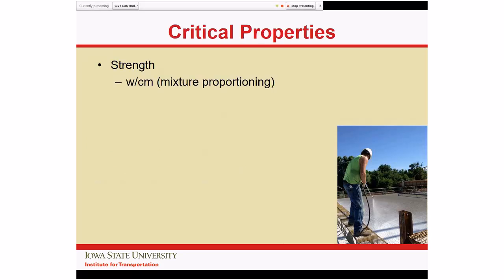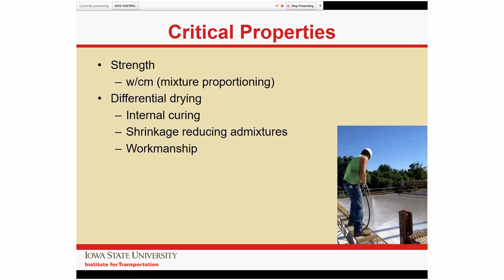So what are the critical properties that we're looking for? As a good engineer, I cannot sleep at night unless I know what the strength is. The fundamental behind this, though, is to realize what controls strength. And the basis is water-cement ratio. It's all about the mixture proportioning. Yes, curing has an effect. Yes, aggregate hardness can have a small effect. Yes, supplementary cementing material dosage can have an effect. But behind all of these, the root parameter we have to control is the water-cement ratio. And basically, the lower the water-cement ratio, the better the strength is going to be.